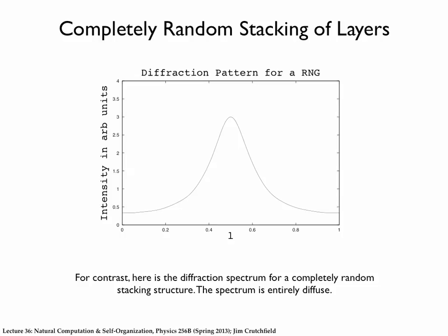I can't really write out the epsilon machine for this as a series of causal state cycles because it's not a crystal structure. The causal state structure for the random process, of course, is just a single state with probability 1/2 to emit a 1 and probability 1/2 to emit a 0. So it doesn't live on any place in particular on the epsilon machine. But if I did have this and found the correlation functions, or if I went to R=3 and tried to write down the probabilities, I would find that the entire epsilon machine would collapse down into a single state.